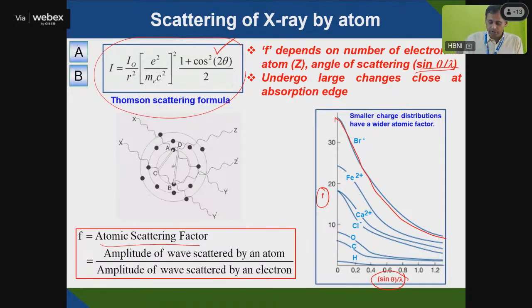As I told in the first class, in case of X-ray, if you take a diffraction pattern, intensity versus 2 theta, at low angle you get the most intense peak, and at higher angle your peak intensity gets reduced. That is mainly because the atomic scattering factor depends upon sine theta by lambda, and the scattering factor is reducing with increasing sine theta by lambda. Because of that, your peak intensity is decreasing.